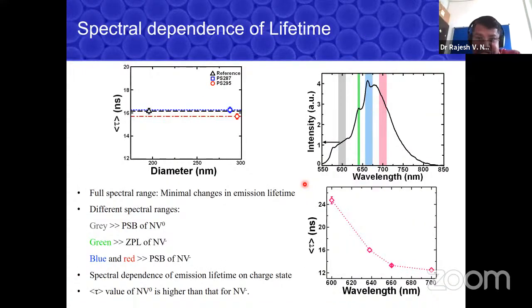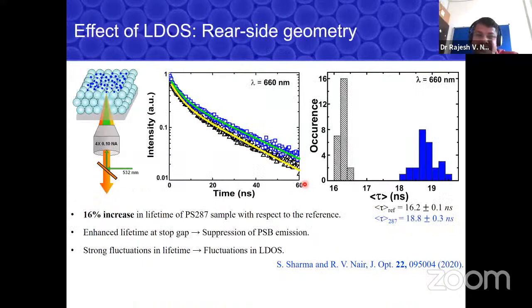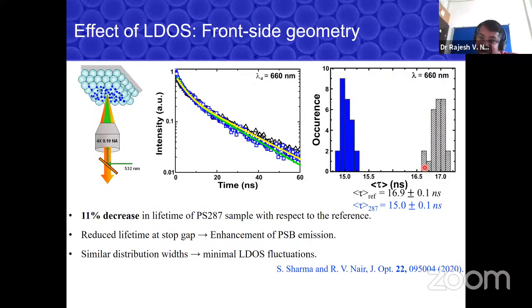Again, we did the lifetime measurements similar to the photonic crystal. We see whether the lifetime of NV centers can be changed. Yes, it's indeed possible that using photonic crystals, similar to the dyes we discussed, I can have an enhanced lifetime. That means there's a gap effect. And we can change the geometry and you can see the lifetime is now reduced because the photonic crystal acts like a reflector. So it is enhancing the emission now.